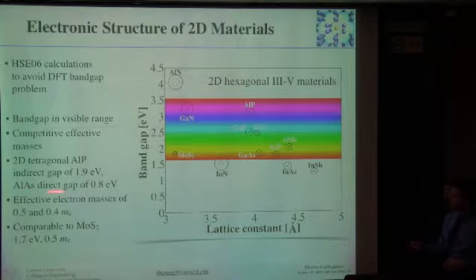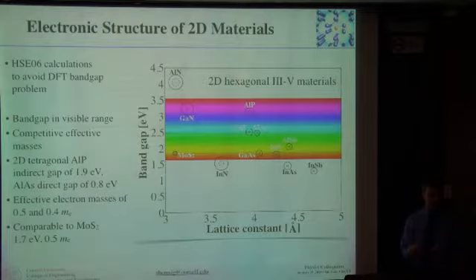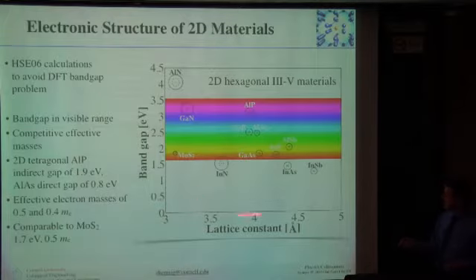We also predict that aluminum arsenide has a gap of only 0.8 electron volt, so there's a range of band gaps. Also for the hexagonal materials, here's the band gaps of the 2D hexagonal materials, which we believe on the right substrate, several of them should also be able to stabilize. By the way, this is a diagram you're going to often see when people from the semiconductor industry present their data, their materials choices, band gap versus lattice constant, so you can see immediately which materials you could stack on top of each other, have similar band gaps.